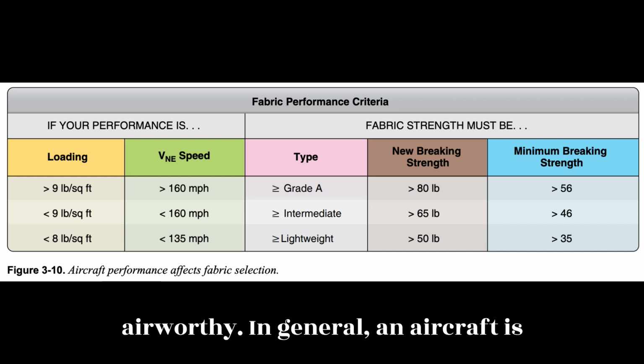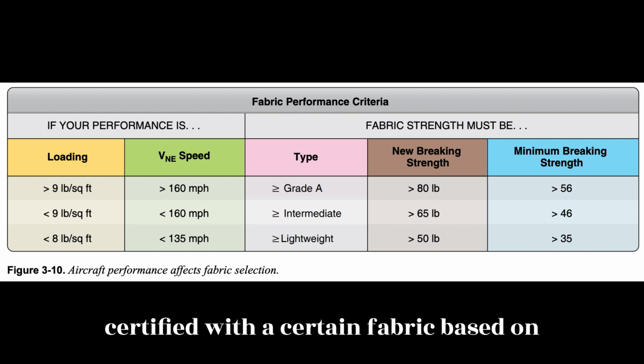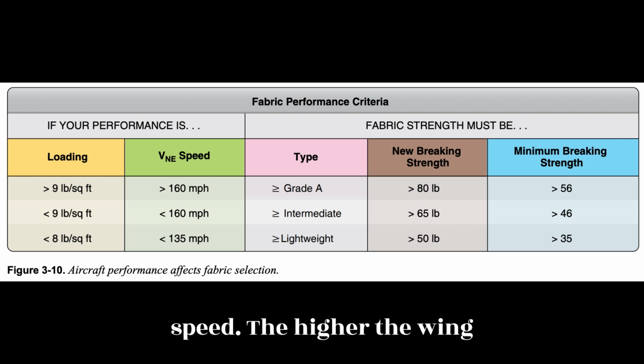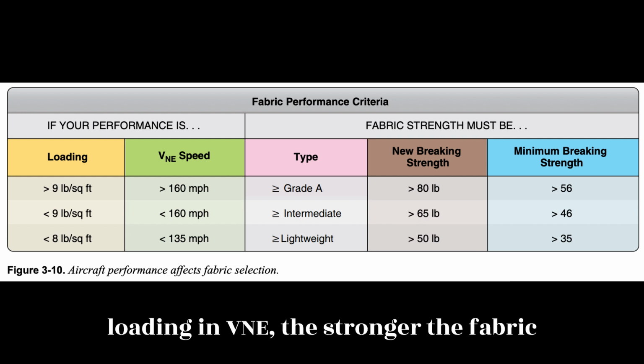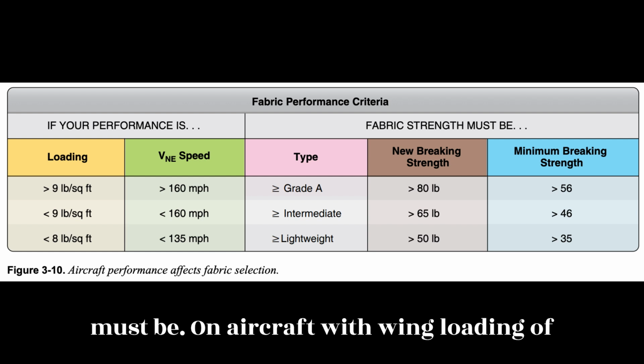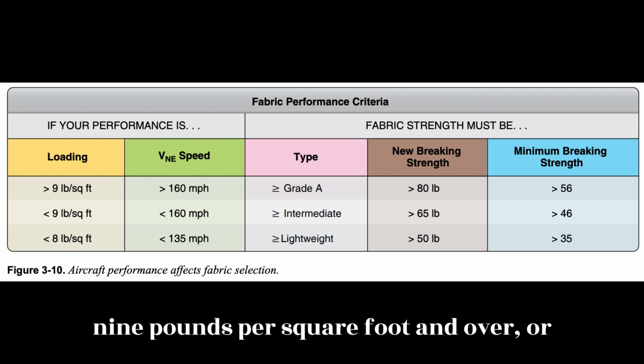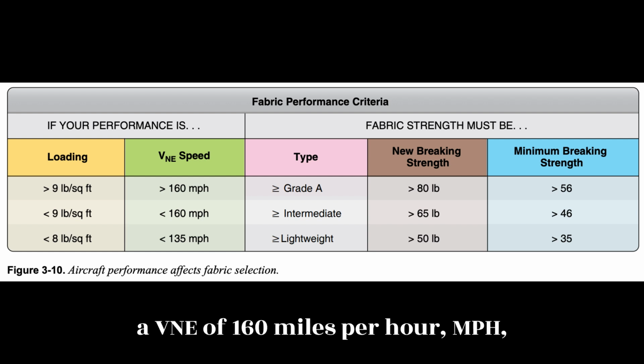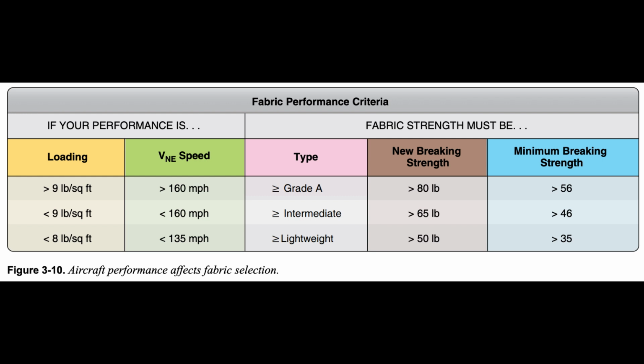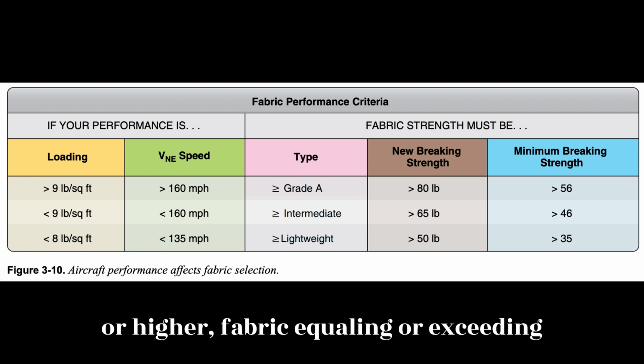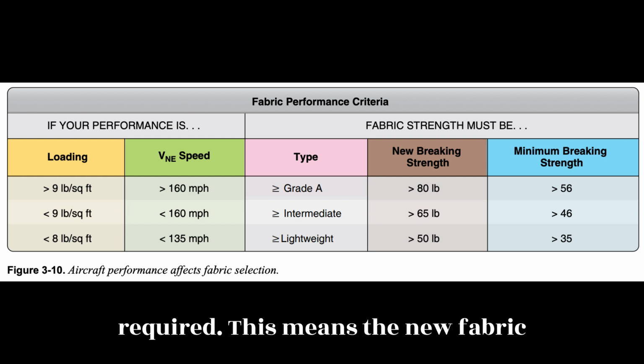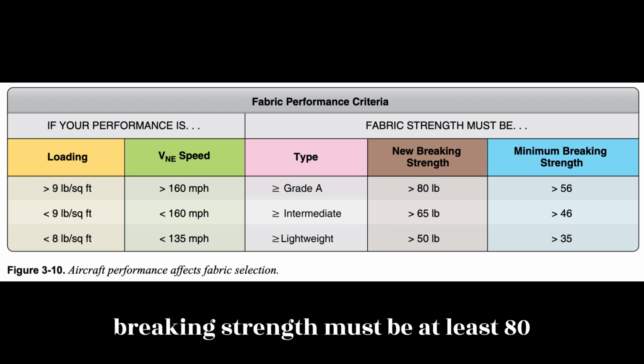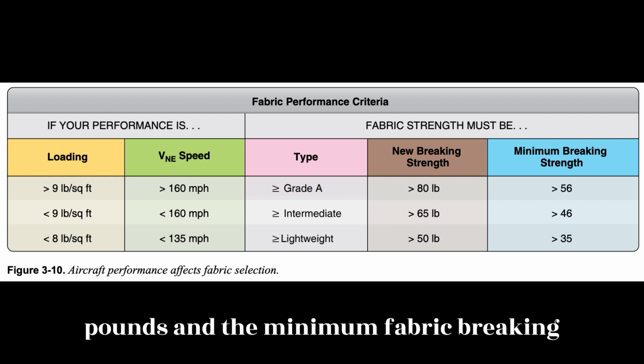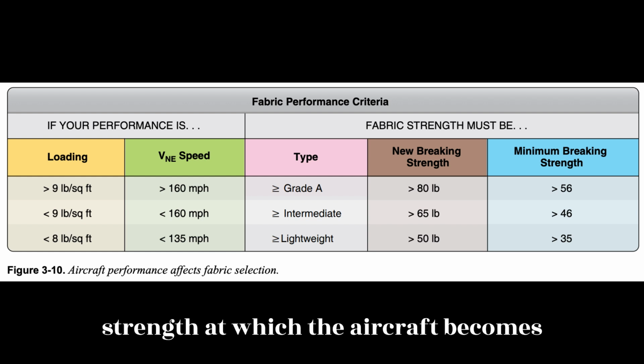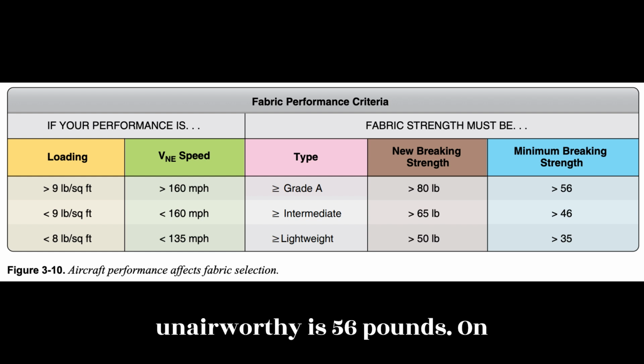In general, an aircraft is certified with a certain fabric based on its wing loading and its never exceed speed, VNE. The higher the wing loading and VNE, the stronger the fabric must be. On aircraft with wing loading of 9 pounds per square foot and over, or a VNE of 160 miles per hour, mph, or higher, fabric equaling or exceeding the strength of grade A cotton is required. This means the new fabric breaking strength must be at least 80 pounds and the minimum fabric breaking strength at which the aircraft becomes unairworthy is 56 pounds.